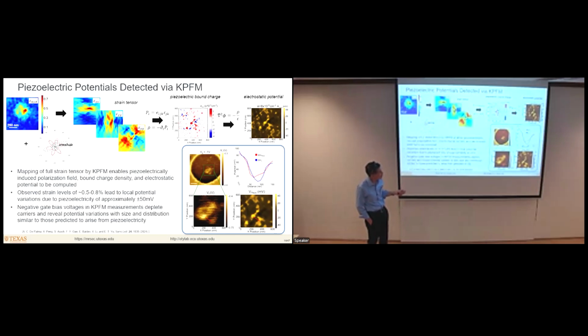If you sort of squint at it, you can see that maybe this looks like a fuzzy version of this distribution over here. And if you look more carefully at, say, this feature here, where there are these two features and then a gap in between in the surface potential, and you look at the corresponding region in the electrostatic potential calculated from the strain over here, that's shown in this line plot. You can see that they actually agree quite well in terms of both the magnitude of the modulation and the spatial extent. So this really quite strongly suggests that what we see over here really are variations in strain and corresponding properties, in this case, piezoelectricity, at tens of nanometers length scales.